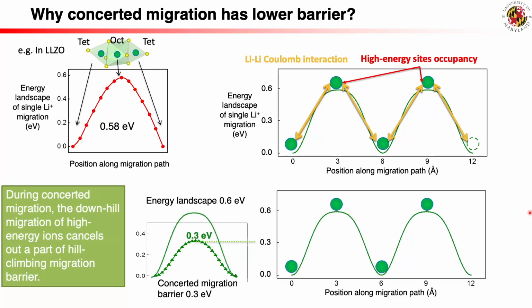It does. And this mechanism of concerted migration isn't limited to just these three materials, right? No, the authors suggest it's a more general principle. They point to other SICs where similar behavior has been seen. Li7P3S11, beta Li3PS4, LISICON, LLTO perovskite, and even sodium-conducting NASICON. So it's not just lithium ions. No, they think this could apply to other ions too. They mention the silver superionic conductor AgI and some oxygen ionic conductors. Interesting. So this could be a really universal mechanism.